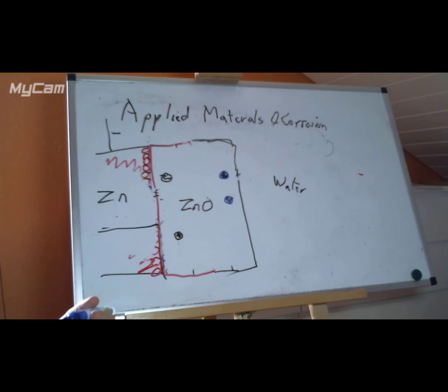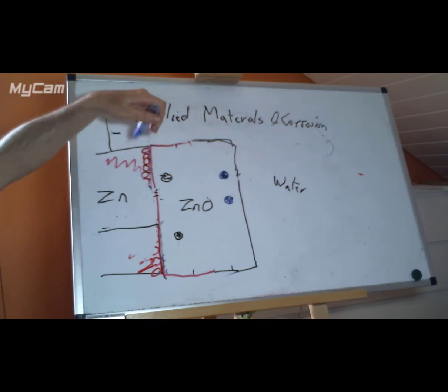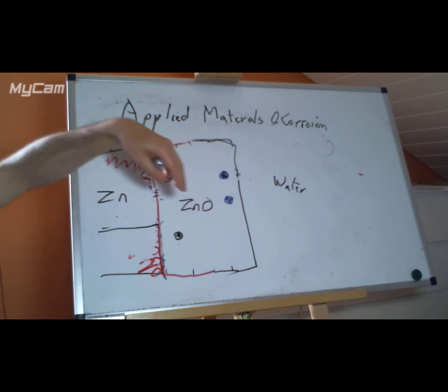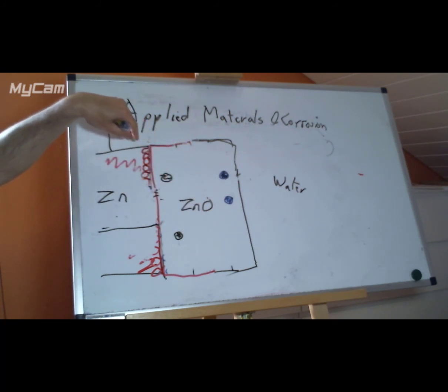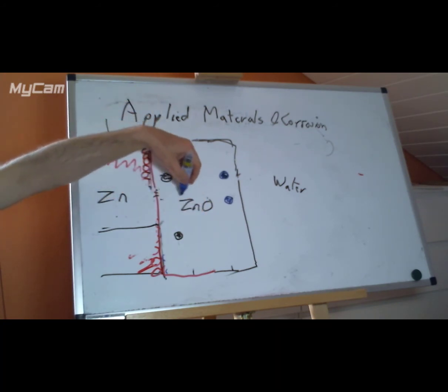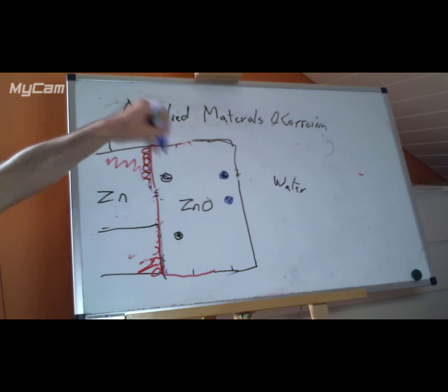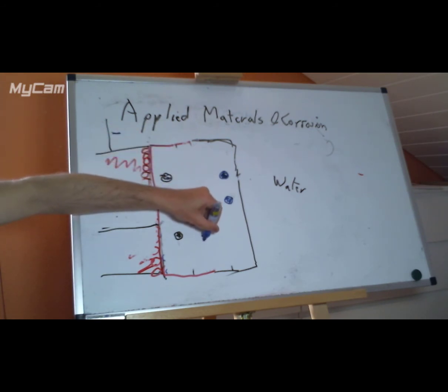If we make it negative, we've got a problem, because our negative electrons, effectively, are going to try to reduce some of this zinc oxide. They're trying to jump onto some of the zinc and make it into zinc 0, and that will make more of these zinc 0 positions. What do we know about zinc 0 positions inside a zinc oxide crystal?